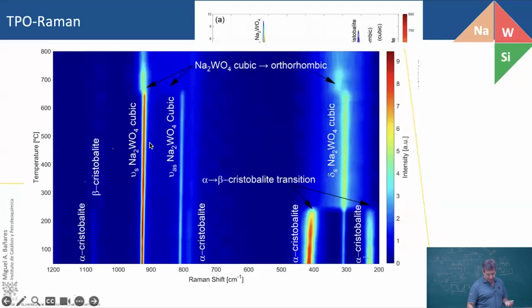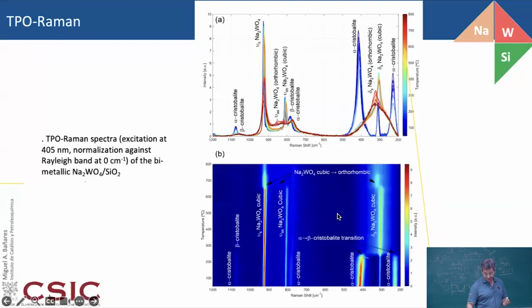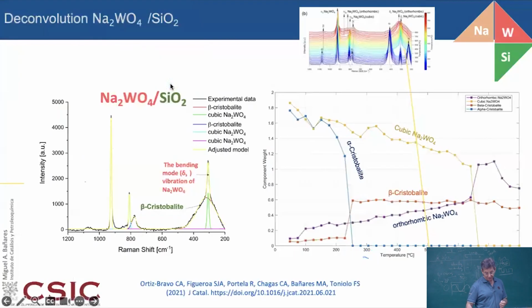You see the sodium tungstate goes from cubic to orthorhombic and finally melts, or the silica support, which is an alpha cristobalite, you see how it is progressively changing, and then all of a sudden there is a crystalline phase change. Here you go from alpha to beta cristobalite on the silica, which accounts for this very broad change, based mainly on the silica support, which maybe you couldn't report from X-ray, but you can from the Raman. And then you see this broad pattern over there.